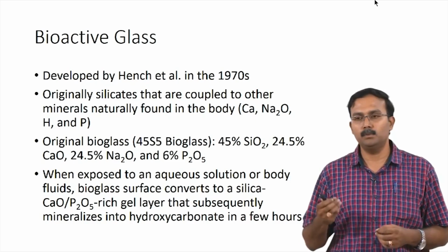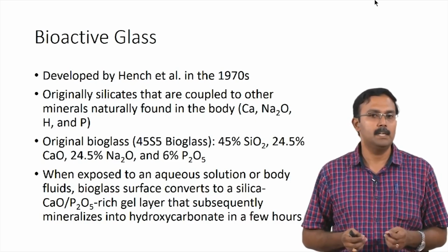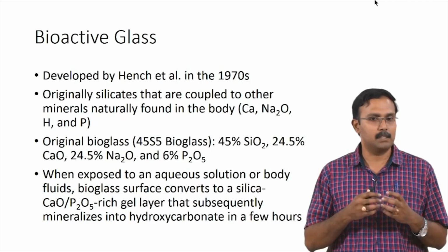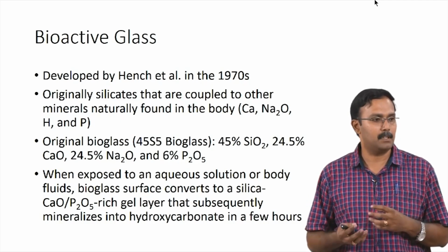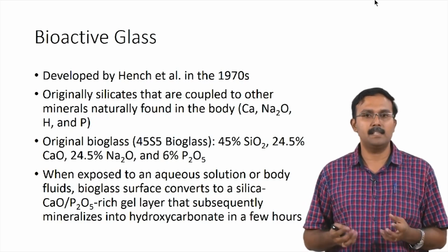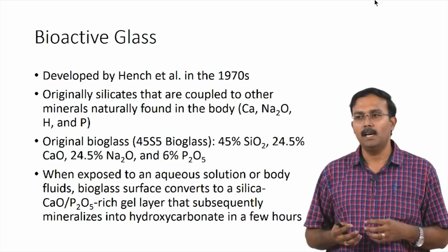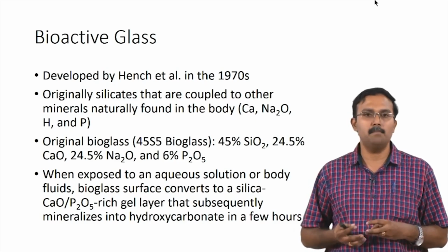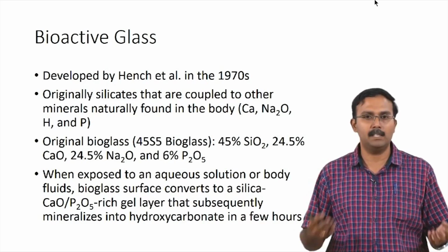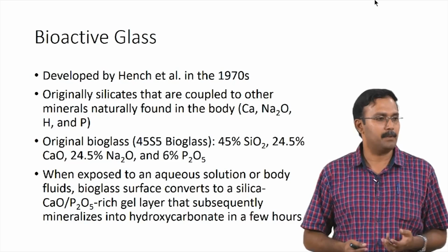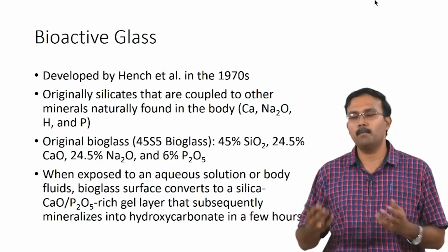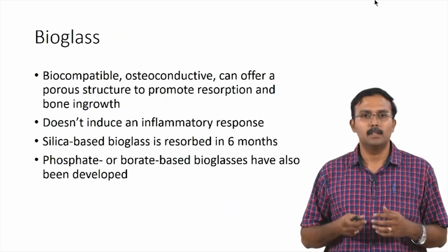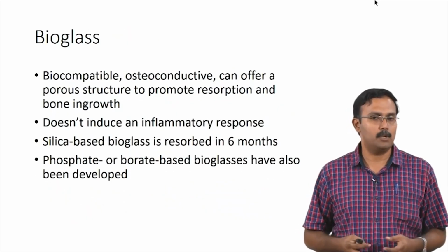When exposed to aqueous solution or body fluids, the surface of this bioglass forms a silica, calcium oxide and phosphorus pentoxide rich gel layer, and this gel layer is subsequently mineralized to form a hydroxycarbonate within a few hours of implantation. Because of this, it promotes bone ingrowth. So, it is biocompatible and osteoconductive.